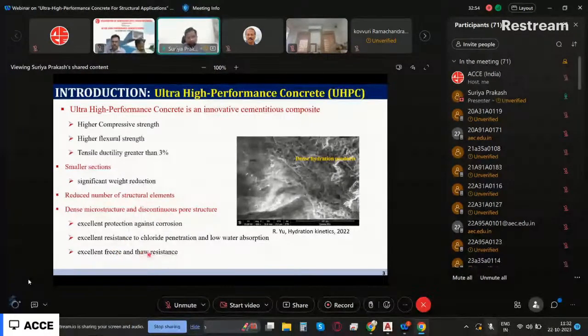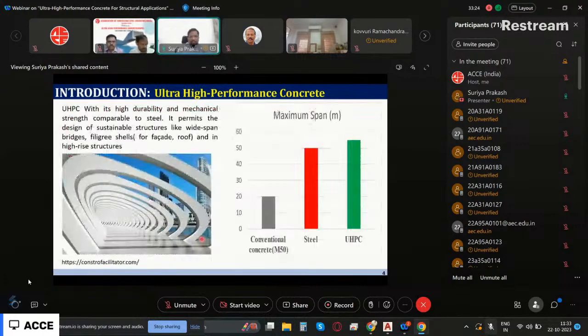The reason is, freeze and thaw is not a big issue in India, but if you look at the Northeast, sometimes the temperature can go below 0 degrees centigrade. There, if water gets inside and then becomes ice, the volume increases. When the volume is increasing, it is going to put pressure on the surrounding concrete and you're going to get a lot of cracking. Now, if water cannot enter itself, then I don't need to worry too much about freeze and thaw resistance. So these are advantages.